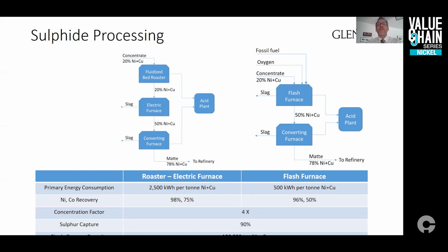In the flash furnace process, the reactions taking place in the roaster and electric furnace are combined in a single furnace. To meet the energy requirements of the furnace, bulk oxygen is required. A small amount of fossil fuel is also typically needed. The product matte and slag are similar to that generated in the electric furnace and are treated in a similar manner. In both flow sheets, the converting furnace slag contains a high concentration of nickel and is treated either in the primary smelting furnace or in a dedicated electric furnace to recover that nickel.